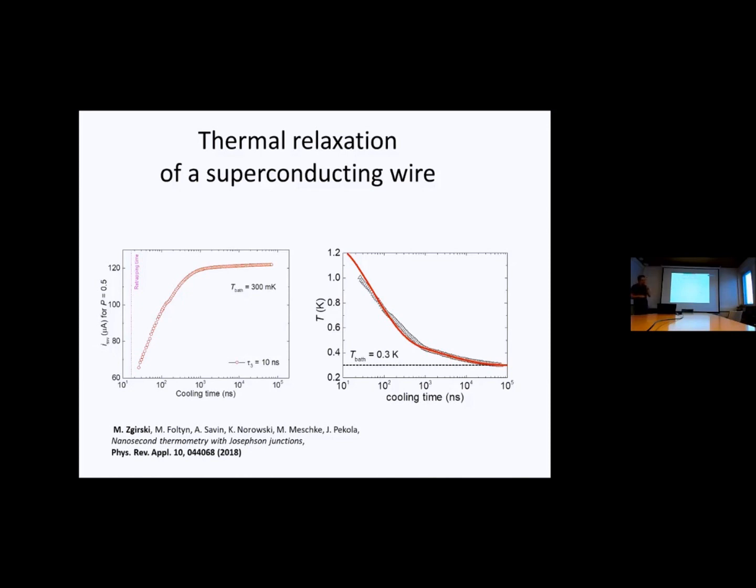Also some hot electron diffusion plays a role, but this is highly nonlinear, because you see here we go from like 1 K to 300 mK. So our parameters are functions, they are not just some values, because we have to take into account heat capacity, thermal conductivity, electron phonon coupling, which are temperature dependent. So it is a highly nonlinear process.